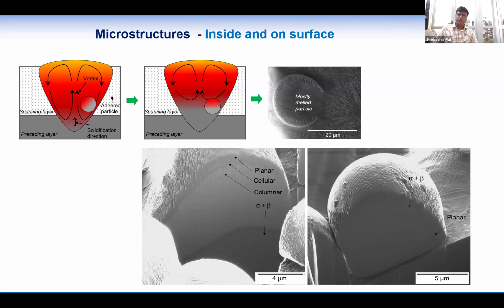So there are a lot of different possibilities in the microstructure, and we can control those things to control the corrosion properties, as it is mostly applied for bone implants, as I told you. So it is much more important to control the corrosion, and that corrosion rate we can control by changing the microstructure.